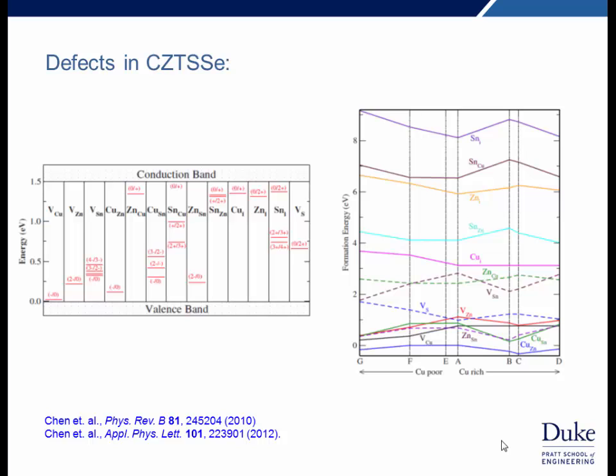Likewise, the copper on zinc anti-site defect is deeper in the band gap compared to the copper vacancy, and with a certain high concentration of these defects, we'd expect this defect state to broaden out and perhaps merge with the valence band, creating band tailing.